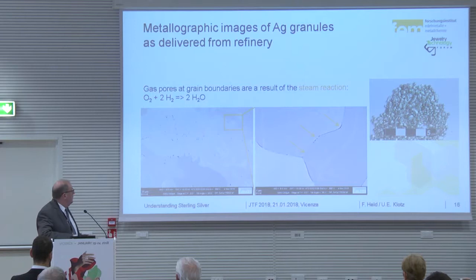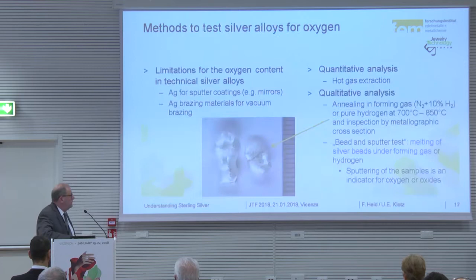Here we have gas pores in silver granules. That's a silver granule, and we see here the small pores. If we look at better prepared samples and we look only at the grain boundaries, we see here the typical problem with oxygen and hydrogen in silver. And this is found in granules. So we know granules contain oxygen and hydrogen, because we cool down the liquid silver in water, so we have both oxygen and hydrogen.